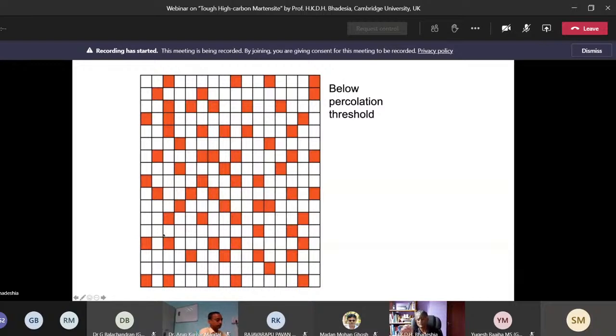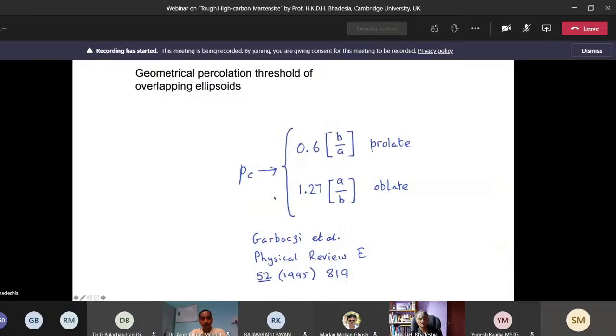Once percolation is lost, you are actually stressing the martensite, the high carbon untempered martensite, and therefore your sample fractures. Okay. And we can calculate the percolation threshold, making certain assumptions about the shape of the austenite. And it turns out that in this structure, we would actually lose percolation at about 10% of retained austenite. So we need to design the amount of retained austenite so that there is a period over which percolation is not lost while the martensite is triggered by the TRIP effect.